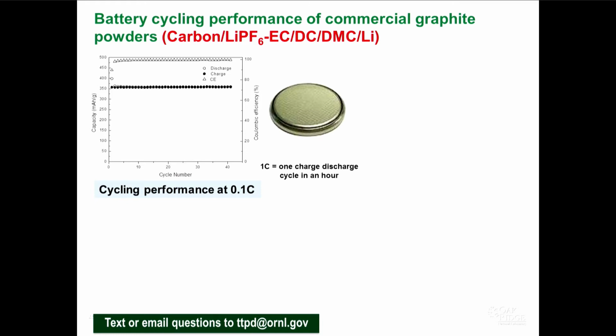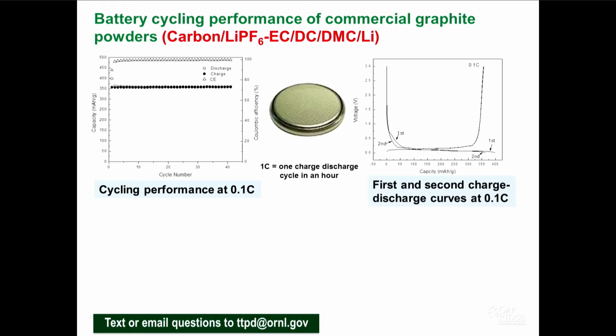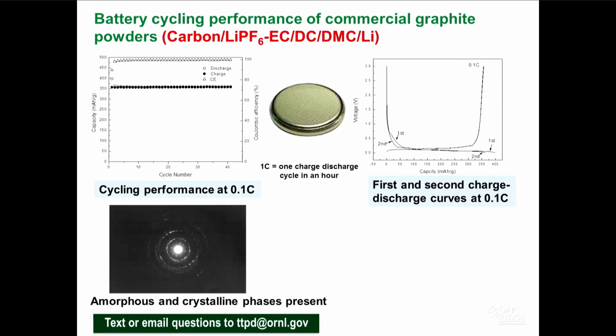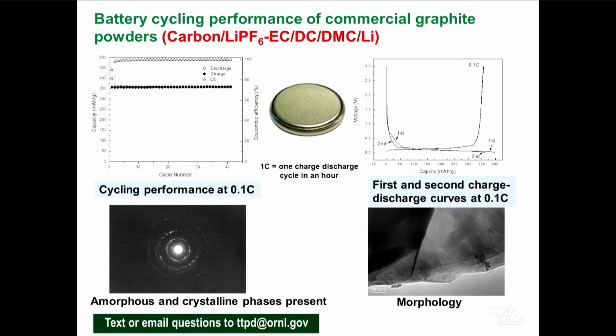And this is a commercial graphite. If you look at the first and second charge discharge curves at 0.1C, you can see the voltage drop, and the first capacity is a little higher, and the second one drops from the first to second. And if you look at the microstructure, both diffraction, amorphous, and crystalline phases are present.